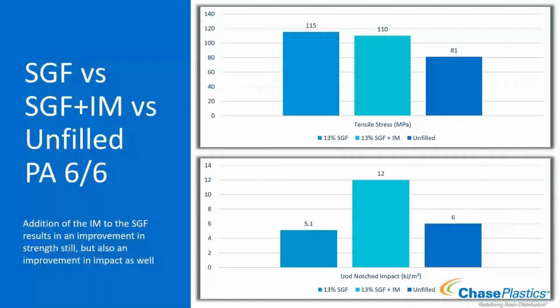So with data for that, we go back to our short glass fiber, but we also include short glass fiber and impact modified values to show you this. Again, your unfilled is using the same grades, so the unfilled is at 81. When you move to a 13% short glass fiber, you jump all the way up to 115 tensile strength. When you add impact modification, it still improves - it's still enough to improve your stiffness and strength, and it gets up to 110. So you're still above what it was unfilled.